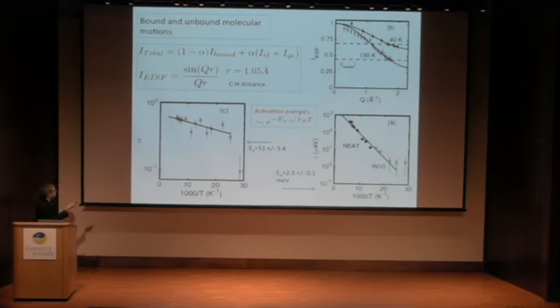Now, I know this is a busy graph, but I'll try to explain what's going on. Up here, I've plotted the elastic scattering intensity as a function of momentum at two different temperatures, 40 and 130 Kelvin. These are temperatures below the orthorhombic to tetragonal phase transition. I've fitted it to a fairly simple model, just what you'd expect for isotropic rotations, but I've fixed the radius to 1.05, which I've chosen to be the carbon-hydrogen distance.